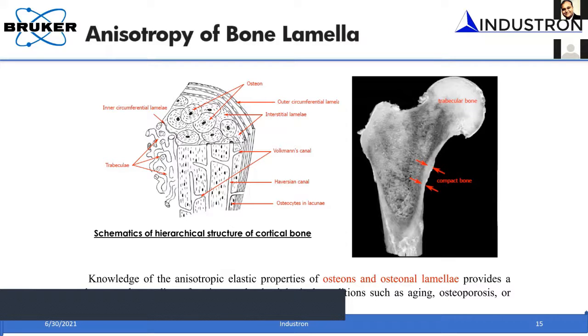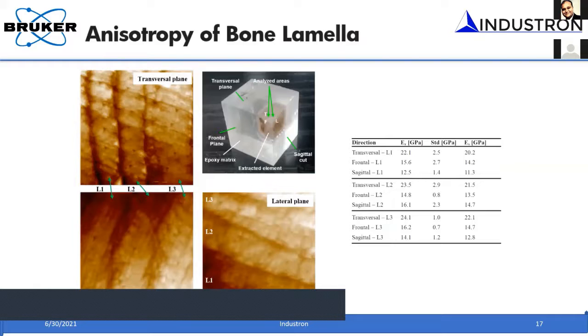So if you measure the properties, you will measure them depending upon the loading direction that you use. One thing that I would advise is, when you do this kind of bone sample, you polish it in 3 directions, the way I'm showing over here. Then you can make a measurement on the transverse plane, the frontal plane, or the lateral plane, in 3 different directions, and you can measure the modulus. That will give you a better understanding of how the anisotropic properties, how the mechanical properties, are changing in different directions.